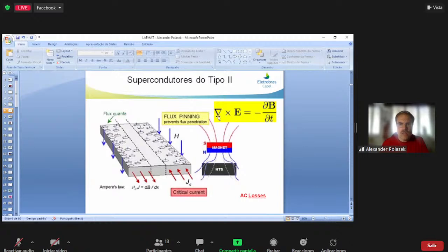Every time you have a variation in the magnetic field, you generate electric potential. That means, in other words, you have to prevent the movement of the flux inside the superconducting region because it causes energy dissipation. And this is really critical for attaining high critical currents in superconducting materials.